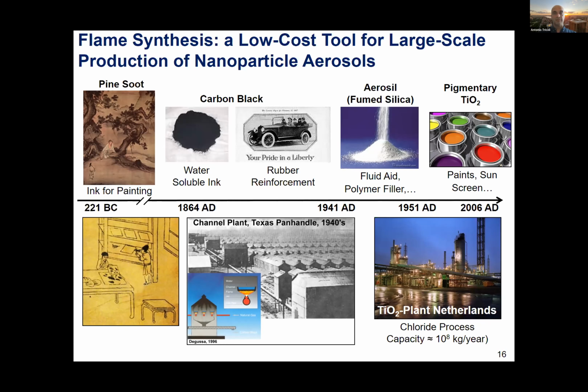And then we have fumed silica, a very important fluidizing filler utilized in many processes, even in toothpaste, and pigmentary titanium oxide, which is the base of all paint, and obviously P25, made by a very similar process, which is one of the most established photocatalysts. So if we use flames for the production of nanoparticle aerosols, basically we can scale up the production of electrocatalysts for electrolysis and water splitting and other fuels very easily. An issue of the system is that they're mostly gas-based, gas-fed. And by being gas-fed, you have limited control on the properties of the nanoparticle and material you can synthesize.